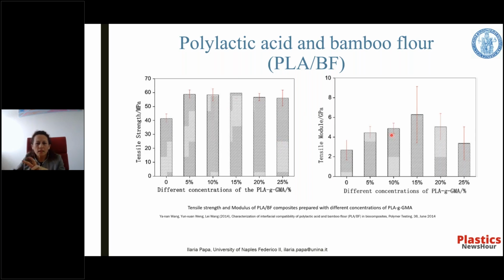In particular, we can see a recorded 44% increase in tensile strength and a higher increase, equal to 155%, of Young's modulus versus the agent-free compound. With the presence of the coupling agent, in this way it's possible to obtain a less expensive compound using renewable and biodegradable biomass. And it led to a close bond between BF, bamboo flour, and the PLA matrix, thanks to the improvement in the mechanical properties of the compound that is observed, with respect to the features of the neat PLA.